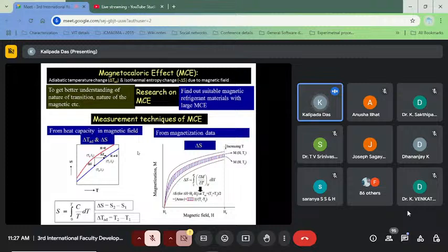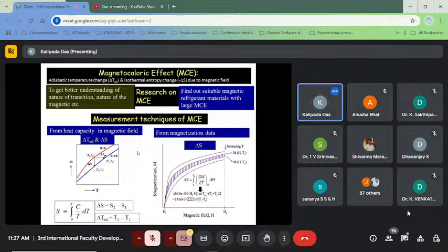Hence, if we measure the magnetic isotherms at different temperatures, then by taking the area under the curve, mathematically we can easily calculate delta S, the variation of the magnetocaloric entropy change with respect to temperature at a fixed field, or at a particular temperature the field variation of the magnetocaloric entropy change. There is another procedure, by measurement of the heat capacity. If we are able to measure the heat capacity of that sample at different magnetic fields, then we can easily calculate the total entropy change over the temperature, and at a particular temperature we can easily get the delta S value, and at a particular entropy we can easily get the adiabatic temperature change of the material. This is the basic phenomenon of the calculation procedure of the magnetocaloric effect.